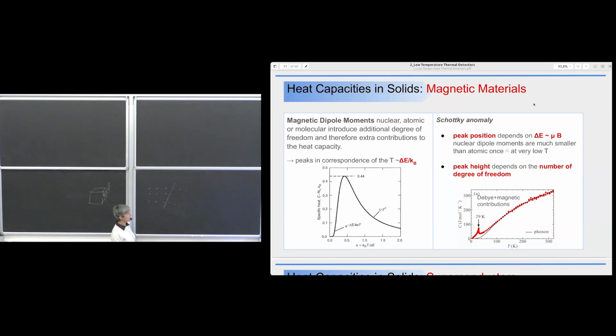So there is a further contribution to the heat capacity that can come from magnetic properties of the materials. When you have a material that has a magnetic dipole in the molecule, in the atom, or due to the spin, you have an additional degree of freedom. And what happens is that in correspondence of the transition where you order your magnetic moment, you have a peak. This is called the Schottky anomaly. The peak position depends on the magnetic field in which your